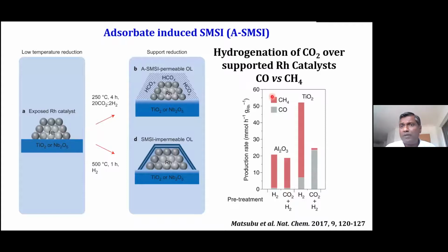This is for CO2 hydrogenation over supported rhodium catalyst. They were hydrogenating carbon dioxide, and the objective was to get as much carbon monoxide as possible rather than methane. So what they did, they treated the catalyst with hydrogen. What they got was a typical SMSI for titania as well as niobium oxide, because they are reducible oxides. And this overlayer is impermeable. So what they got was mostly methane. You can see this is methane selectivity, and this is carbon monoxide selectivity. With the fresh catalyst, they used a mixture of carbon dioxide and hydrogen, and they treated the catalyst, and they formed a permeable monolayer of this metal oxide.